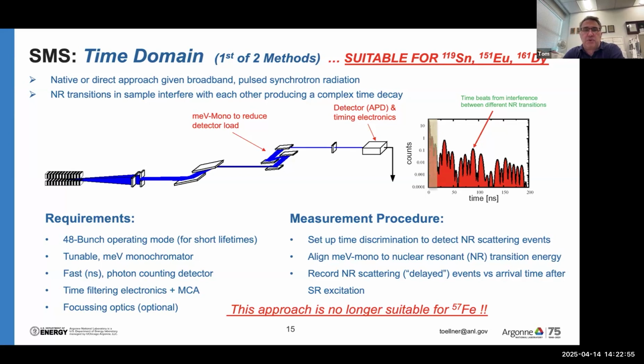This is sort of like the native approach to do nuclear resonance scattering or Mössbauer spectroscopy at a synchrotron, given it's a broadband pulse, a pulsed source. You excite all the resonances in the sample, and they interfere with each other. So it's an interferometric approach, which leads to a rather complex time decay, but doesn't involve introduction of any other resonant absorber in order to determine the hyperfine structure.